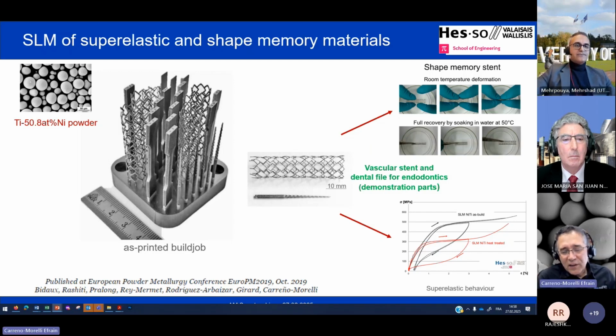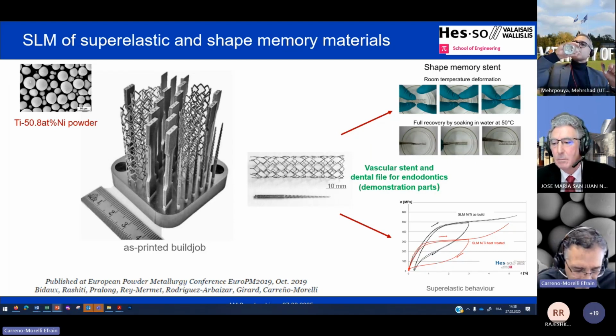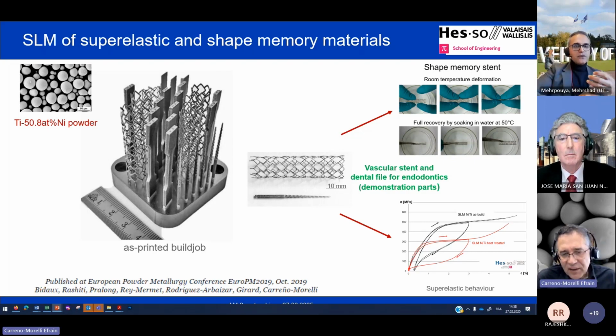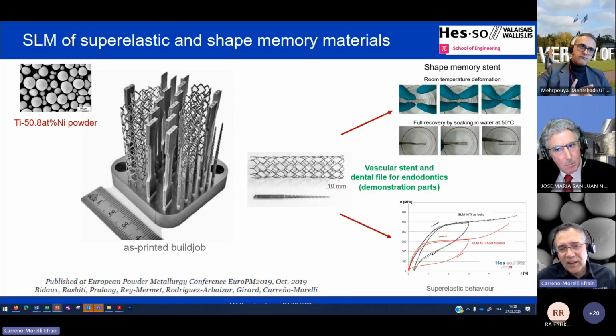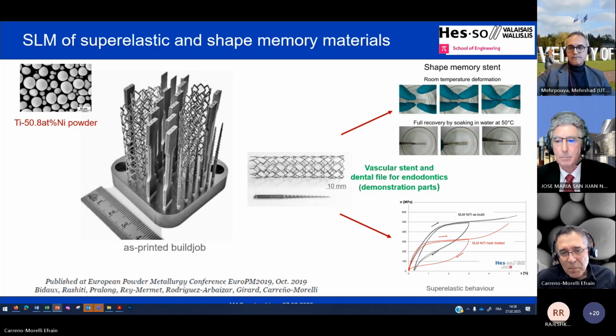Yeah. Binder jetting is very nice for mass production. It is much more convenient than the laser powder bed fusion techniques, in our opinion. The challenge comes mainly from the contamination because of the binder or the printing condition, and then the debinding and sintering conditions. These are the main challenges. But it's a technique which offers reduced roughness compared with the laser-based techniques. Then, yes. Okay, thank you very much.